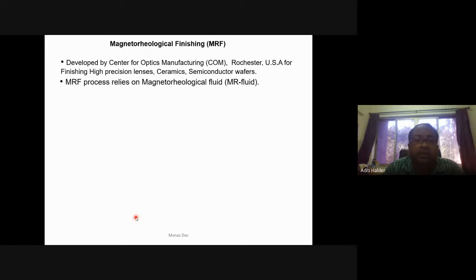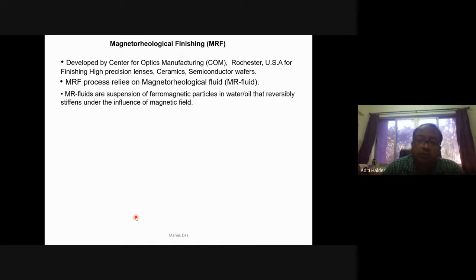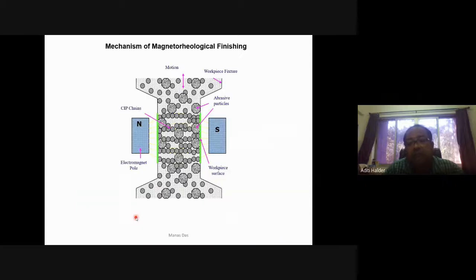It works on the basis of a magnetorheological polishing fluid. In this MR fluid there are ferromagnetic particles, which are called carbonyl iron particles. The next slide I can show you. And you make this a polishing media, so you mix abrasive particles there. These abrasive particles may be silicon carbide, boron carbide, or diamond, depending on what kind of material you are using. So you can choose your abrasive particles. Depending on the hardness of the workpiece material, you have to use abrasive particles of higher hardness.